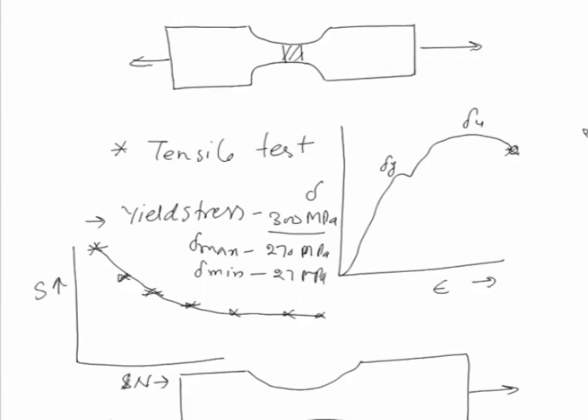So, if it is tension to tension, then the minimum stress will be 27 MPa and the maximum stress will be 270 MPa, and accordingly the stress range can be calculated. This is one way which can be used for conducting the fatigue test. There is another way, when we know that the material is not a ferrous metal system, like aluminum, and will not be getting a clear-cut endurance limit.